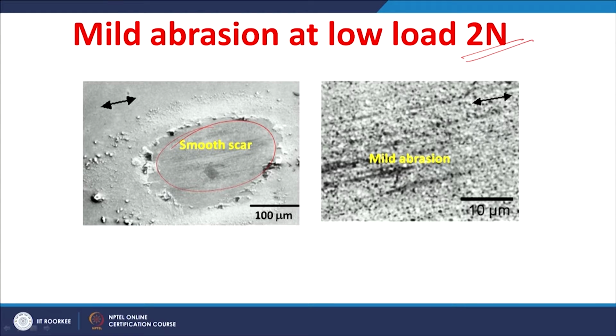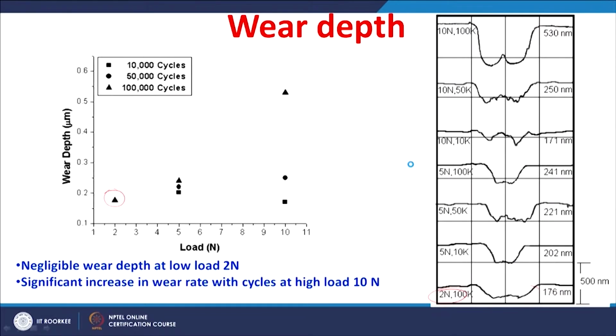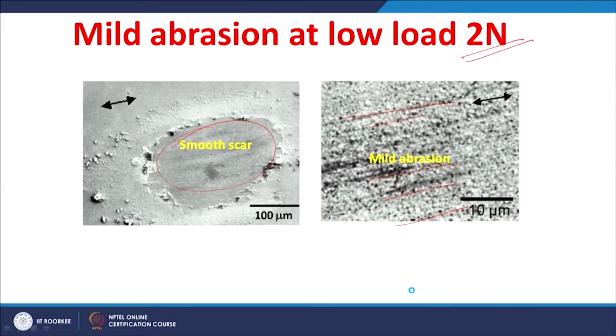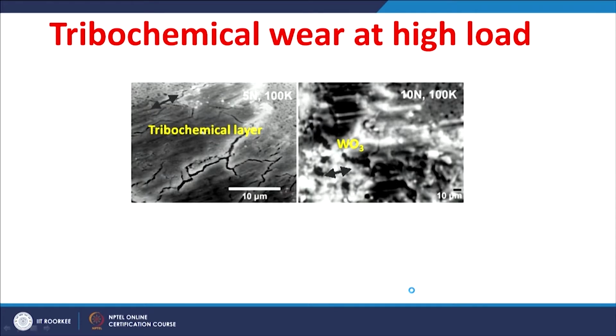a high magnification image of the same surface shows there is a mild abrasion. There is an abrasive groove. So, you have an abrasion which is mild at the lower load of 2 Newton. It also agrees with the information we obtained with the wear depth. The wear depth is negligible at a 2 Newton load after 100,000 cycles, whereas at higher load the worn surface shows a significantly different characteristic than that obtained at the lower load. At higher load the worn surface is mainly covered by a layer, and the layer is different in contrast from the worn surface.